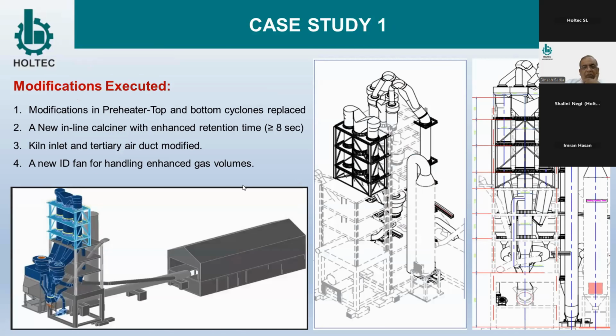So the major modifications which were done were top cyclone replacement and a new complete calciner which has a residence time of more than 8 seconds. Kiln inlet and tertiary air duct also were modified. And of course, an ID fan with higher capacity was installed to take care of additional volumes. If you see the diagram, the new calciner is outside the existing preheater building, and the top stage and bottom stage cyclones also were modified accordingly, along with the new inline calciner.